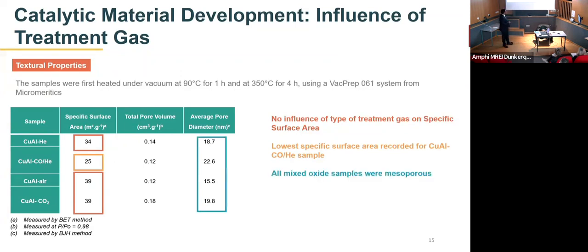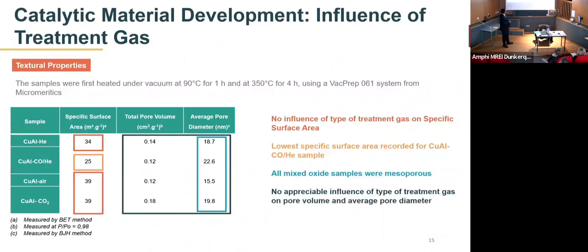The other property that we compared for the samples was the average pore diameter. Here you can see that the average pore diameter lies well within the mesoporous range, so we can say that all our materials were mesoporous. And finally, if we compare all the samples for the total pore volume and average pore diameter, we don't see an appreciable impact of the type of treatment gas on the textural properties of our mixed oxide samples.